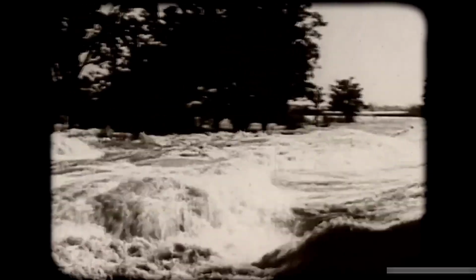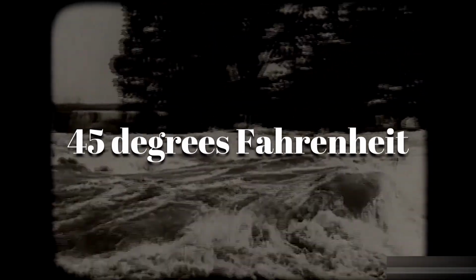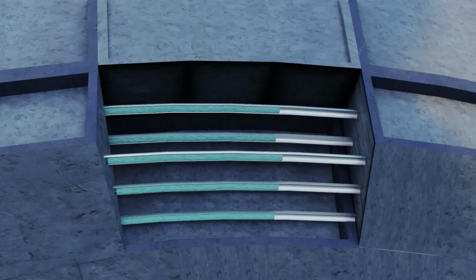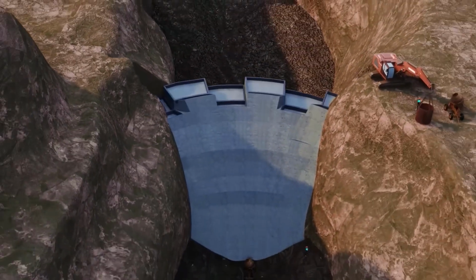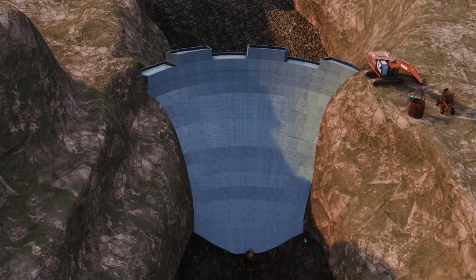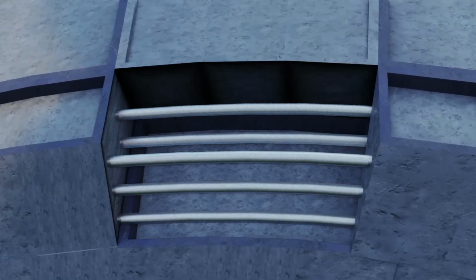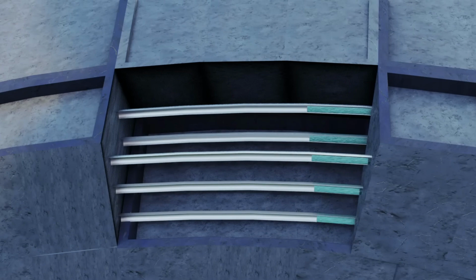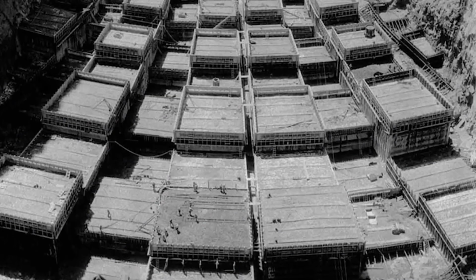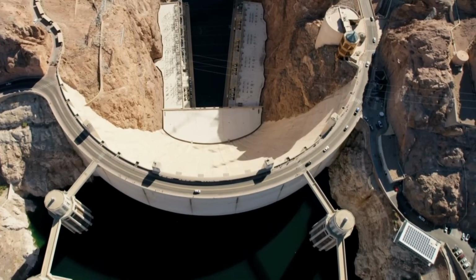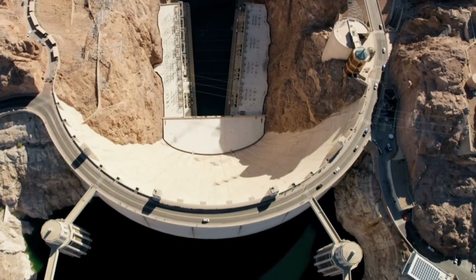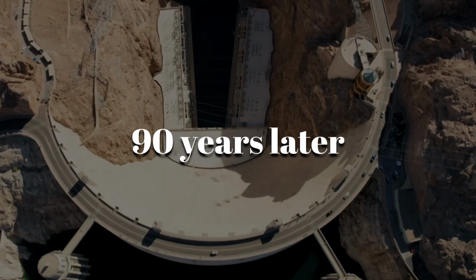After each block was poured, chilled river water, kept at around 45 degrees Fahrenheit, was pumped through the pipes. This pulled excess heat from the concrete, allowing it to cool and cure evenly in just weeks rather than decades. The cooling system was a groundbreaking innovation, one of the first of its kind on such a massive scale. Thanks to this clever engineering, the Hoover Dam's concrete remains crack-free and rock-solid nearly 90 years later.